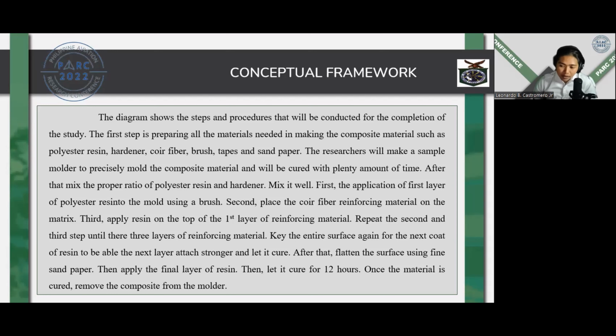After that, flatten the surface using fine sandpaper, then apply the final layer of resin. Then, let it cure for 12 hours. Once the material is cured, remove the composite from the molder.